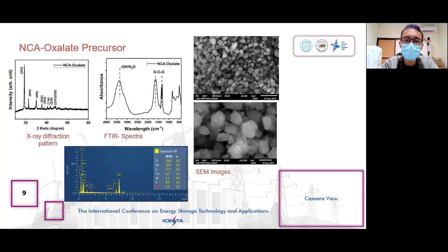Result and discussion. To assure the formation of the oxalate precipitate of NCA, the dried precipitate was analyzed using XRD, FTIR, and SEM. The XRD peaks can be attributed to nickel oxalate dihydrate compound provided in the figure. The peaks observed are highly crystalline, indicated by the sharp peaks. Infrared absorption pattern also confirms the presence of oxalate. The as-prepared NCA oxalate powder is loose, with quasi-cubical shape and smooth surface. The edge of the particle as well as the grains can be clearly observed.